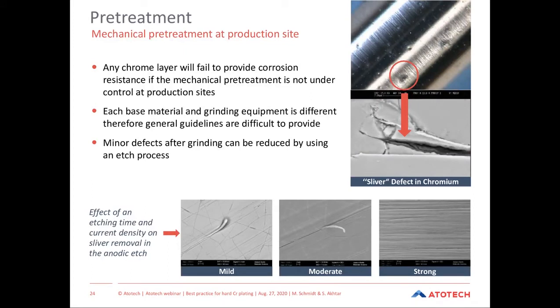Here you see some defects. On the top right side, you can see some defects like slivers which can be produced in the pre-grinding operations. An etching process as the last step before the chrome plating can reduce or remove some of these slivers or defects, but it's usually not able to cover everything. So in the optimum case, these kind of slivers or defects are removed in the pre-grinding operation.